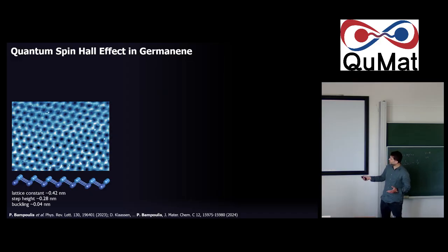Okay, so you can see the scanning tunneling microscope image over here. You can resolve the honeycomb lattice, and you can see that it's actually buckled. You see that half of these atoms are brighter than the other half. Of course, you're talking about STM here, so characterizing this buckling is a little bit difficult because you also deal with the density of states. But you still can make out the lattice constant, which is about 0.42 nanometers. That's what you would expect for a low buckled germanene lattice.